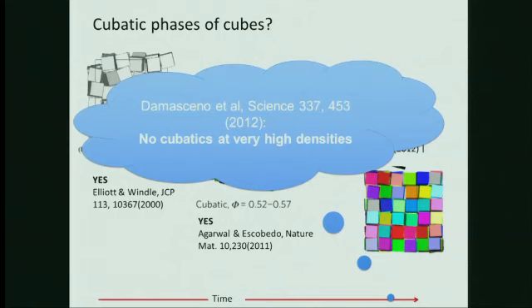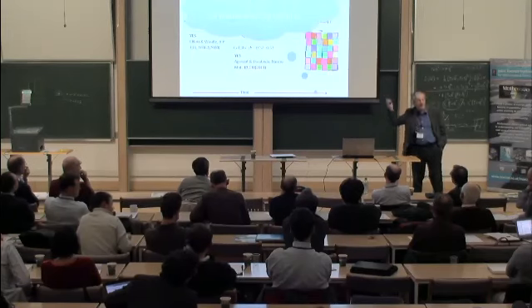Last year looked at how many shapes? 200? I don't know, a huge number of shapes. And they found that if you take cubes, but you go to really high densities, that they form a crystal, which I guess is what you expect. And I don't think that you investigate the lower density behavior, but so you, well, we did look for the cubatic phase because of Escobedo's work, and we definitely don't reproduce his results, but we reproduce Dijkstra's. Okay, good.